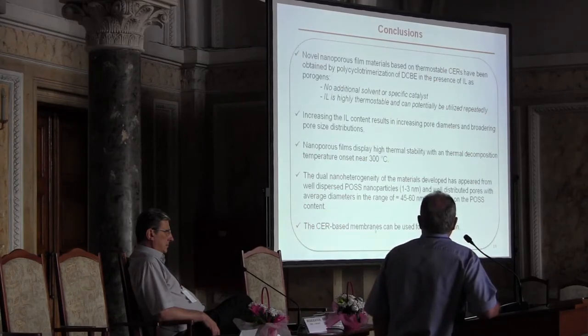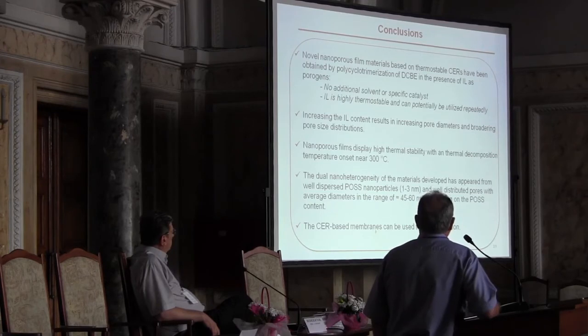Finally, conclusions. Novel nanoporous film materials based on thermostable CERs have been obtained by polycyclotrimerization of the dicyanate ester of bisphenol E in the presence of ionic liquids. Increasing the ionic liquid content results in increasing pore diameters and broadening pore size distribution. High thermal stability was found, and the dual nanoheterogeneity as well, as I said before, and the CER-based membranes can be used for gas separation.